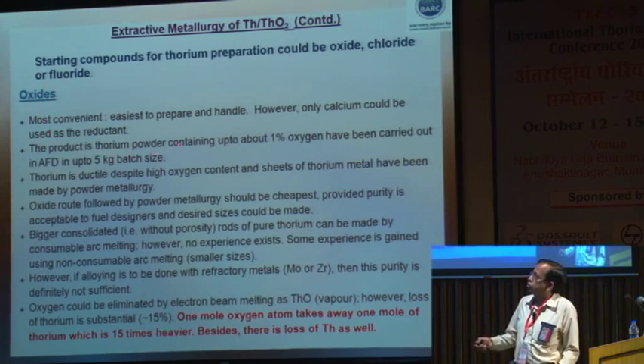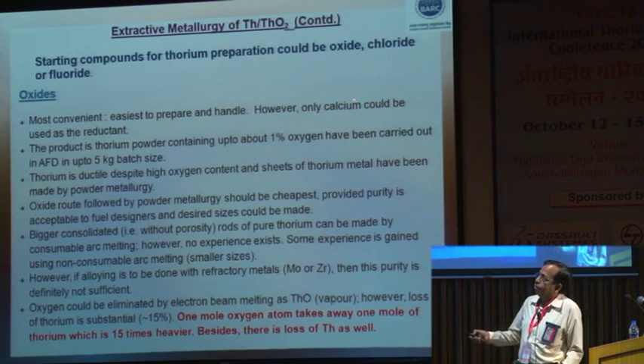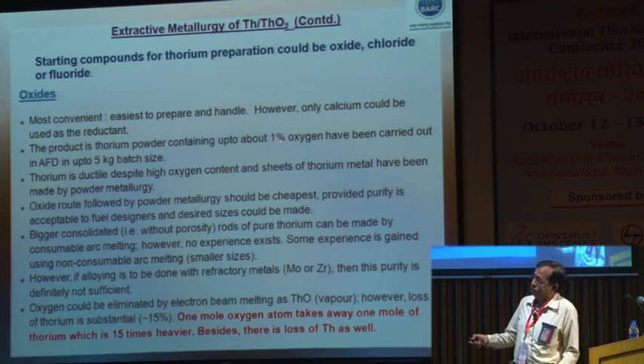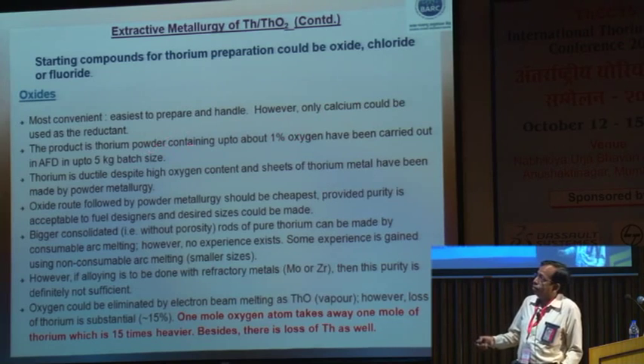So oxide was reduced using calcium as the reductant, and what we could get is a product having 1% oxygen. So the oxygen level was slightly on the higher side, and this could be made into different shapes, for instance, a sheet by powder metallurgy. The powder metallurgy route is better suited, because melting and casting, for instance by consumable arc melting, would require a special type of facility, and we don't have any such facility with us. We have some experience of non-consumable arc melting of thorium at the moment on smaller sizes.